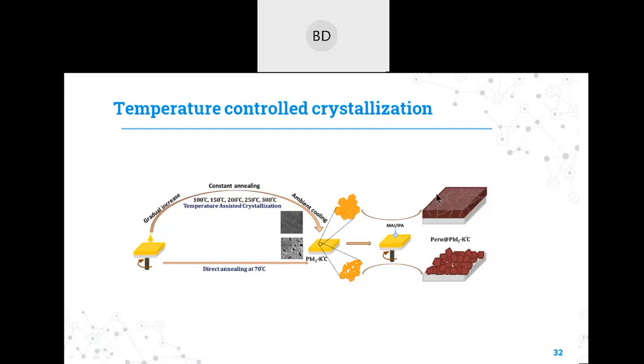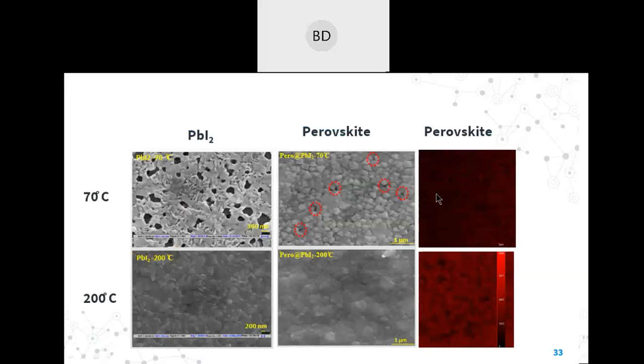a very good perovskite. So out of it, we came to know that the PbI2 which is annealed at 70 degrees centigrade has this kind of morphology. But if we anneal it at a higher temperature, in our case, we annealed it at up to 300 degrees centigrade, out of which 200 degrees centigrade gives a better performance, and this shows this kind of PbI2 morphology. If you see here, there are hardly any pinholes visible in this structure.